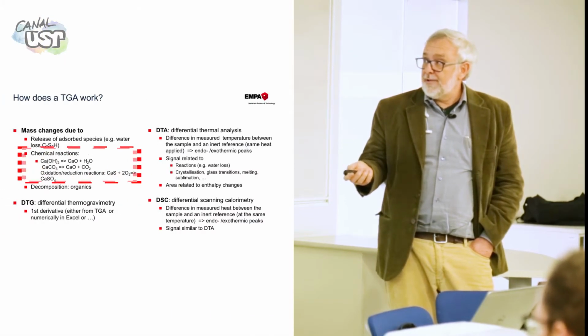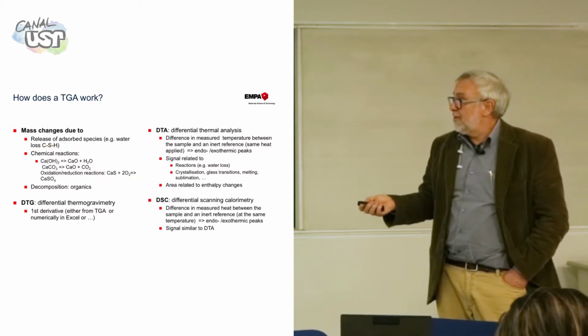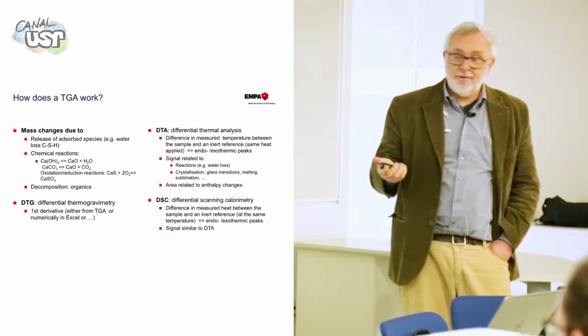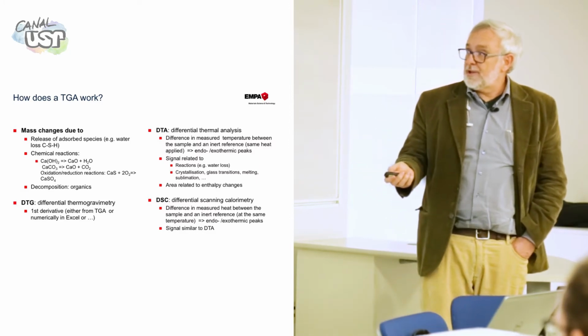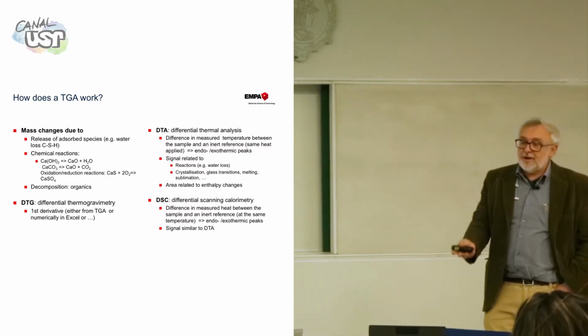Mass change also comes from chemical reaction. If you heat calcium hydroxide, portlandite, it's going to decompose around 550, depending on your TG. You decompose calcium carbonate, you decompose magnesium carbonate, each at different temperatures. You can also have oxidation. If you have oxygen inside and you're dealing with slag, you can have oxidation of sulfur, and then you get weight gain in the system. It happens. So some machines allow you to make a vacuum first. You remove the environmental air and then you pump in nitrogen.